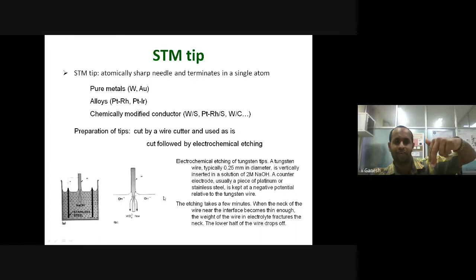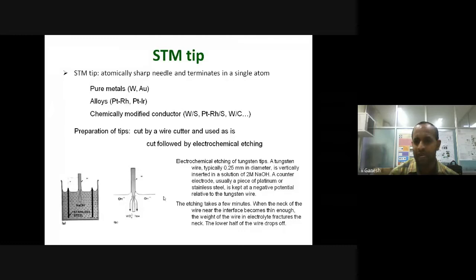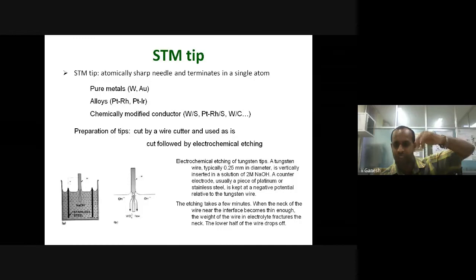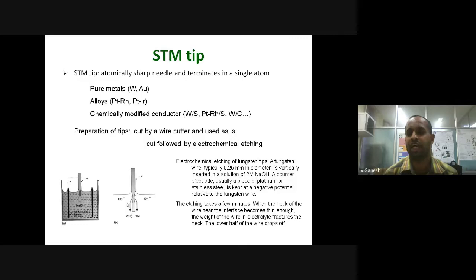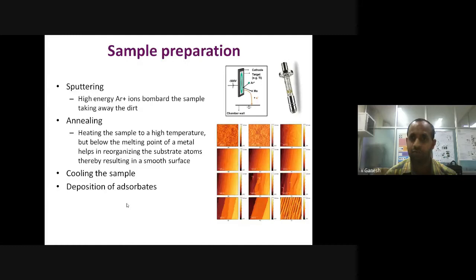You can simply dip a tungsten wire into an alkaline solution like KOH or NaOH. Using a potentiostat, you can apply a voltage of about 2 or 2.5 volts. Then at the electrode-electrolyte interface, rather the solid-liquid interface, there would be bubble formation. The metal undergoes etching, dissolution, so that within a fraction of a minute or two, you would get an atomically sharp tip. This will break into two pieces. One would be standing slightly above the solution, the other inside the solution. In fact, both could be used as an atomically sharp tip to image in STM. Okay, so this is the mode of operation.